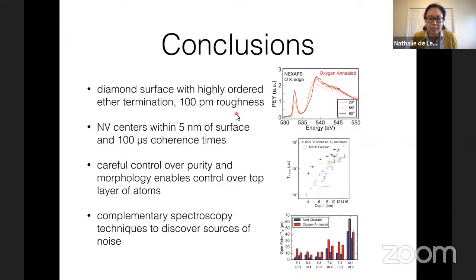But the two that are easiest to make are oxygen and hydrogen. So oxygen you sort of get for free, because if you just acid boil the diamond, which is what you have to do to clean it before you get started, then you get this horrible mixture of oxygen states. So what we were doing was just trying to take that mixture and turn it into something that was much more well-ordered. Hydrogen you also sort of get for free in that diamonds are grown in a hydrogen-based plasma by CVD. And they come out hydrogen terminated, which also means that you can just put them back in plasma and re-hydrogen terminate them.